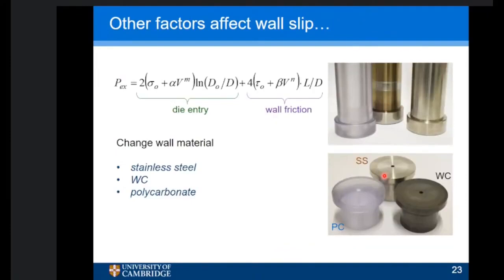So what else might affect wall slip? Well, what happens if we change the wall material? Typically, you will do experiments in a lab with something like a nice bit of stainless steel. What happens if your machines are actually made from a different material, stainless steel or tungsten carbide or even polycarbonate? Because we're always talking about interactions between the material and the wall, so the nature of the wall will become important. So actually what we have is 3 sets of identical apparatus. This one is made out of polycarbonate, this one is made out of stainless steel, and this one is made out of tungsten carbide.